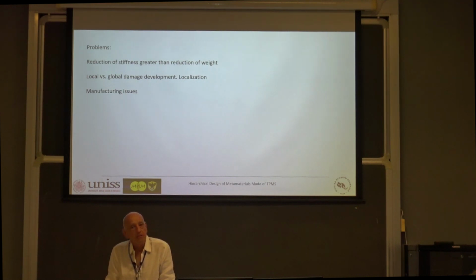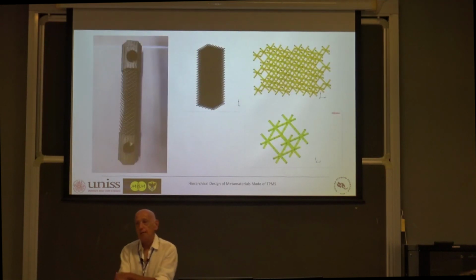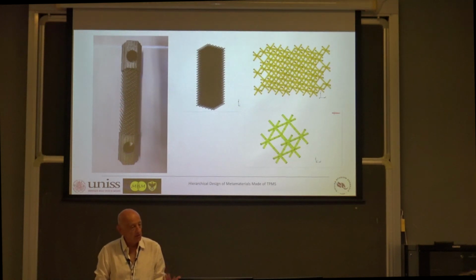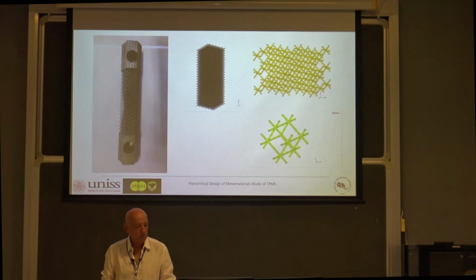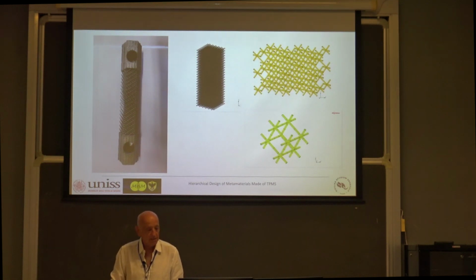In almost all these materials, we have localized damage development. There's a competition between local and global damage. Sometimes this is desirable, sometimes it is not, depending on the application. And there are manufacturing issues. In order to show that, I will present a small experiment. We produced this sample. The sample is made of titanium, a lattice made by cubic cells. During manufacturing, spheres were placed in the joints so that we could have an improvement of properties in the nodes.